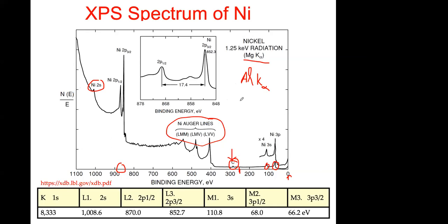So the good thing to have what is called a dual anode source, to have a magnesium K-alpha and aluminum K-alpha source, is that you can change the X-ray source, and you will see this. If you see a peak moving, it definitely is an Auger line. So it's a very easy way to identify Auger transitions and not get confused. So that's the advantage of having what is called a dual anode source.